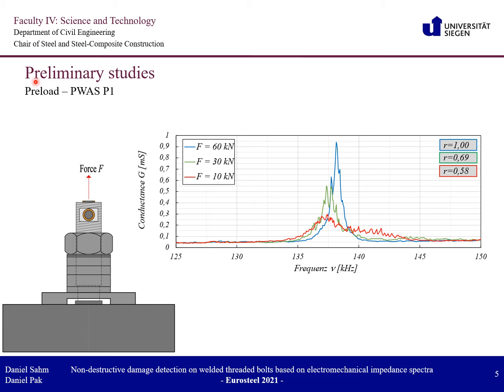In order to detect the loss of preload, the spectrum with the full preload force was chosen as reference and served as baseline. It can be seen that an increasing loss of preload results in a reduction of the correlation coefficient. If the pretensioning force is reduced from 60 kN to 30 kN, the correlation is only 69%. If the pretensioning force is reduced to 10 kN, this results in a correlation of 58%. The measurement results are plausible and show that the detection of loss of pretension with the help of electromechanical impedance spectra is basically possible.